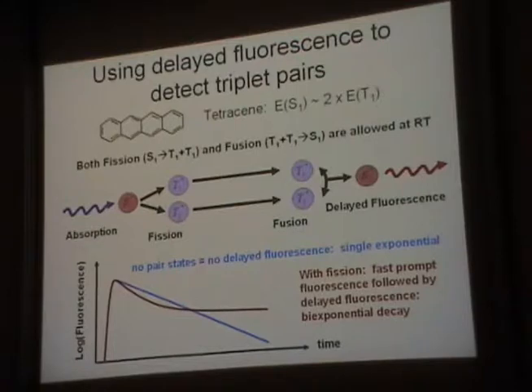So the next question is, these are molecules, how do we detect it? Tetracene has this nice feature that I was mentioning before. The singlet and the two triplets are comparable in energy, so you can actually go back and forth between them. So you can absorb a photon, create a singlet state, split into your two triplets. So you can see some fluorescence here. The two triplets are dark. They'll go along for a while, but it's thermally allowed for them to recombine later and recreate the singlet at some time later. That's called delayed fluorescence. And it's delayed by the lifetime of the triplets, basically.